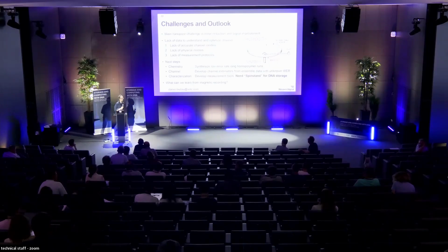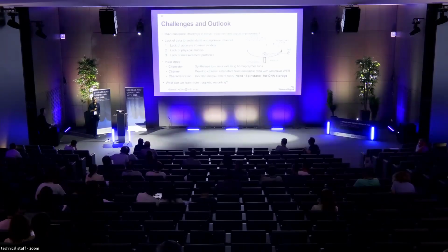So that's, of course, a hard question. You know that as well as I. Just to throw out some numbers here, typically with these membranes we can go down to maybe 10 nanometers, and below that you get all kinds of stability problems, or they break. Probably you can push it a little more, maybe to single-digit nanometers, I would say that's where it probably ends. Maybe you can make something that's locally thinned. It's not an easy lithography thing, but again, you know that much better than I do.